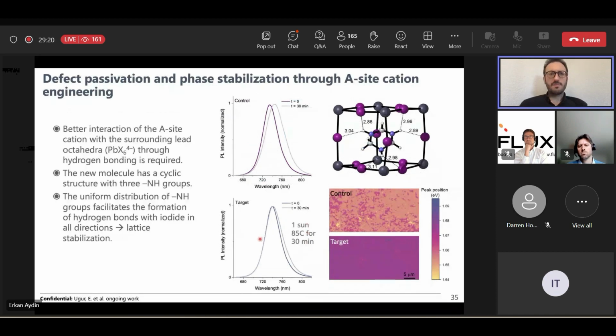Well, very recently, this is ongoing work, and rather than the contacts, we also focus on the bulk of the perovskite. So here, what we have done, instead of using the typical methylammonium, formamidinium, cesium, Rb cations, we start to use a high pKa cation in the bulk. We use this cation as an additive. I'm not able to express the name at the moment because this is under submission. But basically, this enabled us better defect passivation in the bulk, because the molecule is a cyclic structure, and it has 3 NH groups, and these NH groups are forming hydrogen bonds with the iodide in multiple directions, and it's well anchored to the cage, which is quite favorable. And it's also helping for enhanced stability.